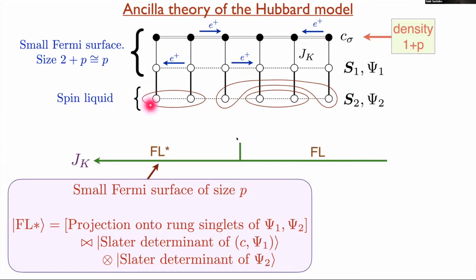And now I can even write down a very simple wave function. In fact, this is for the case that there's a spinon Fermi surface here. So what I do is I form a Slater determinant of C and psi, the top 2 layers, just like I did in the heavy Fermi liquid. And then I form a Slater determinant of psi 2. And then I project, and this is, of course, the hard part, project onto rung singlets of psi 1, psi 2. So now you can see from this wave function, which we've never had before for a single band FL star state, it's a wave function on the physical electrons. Everything out here is projected out.